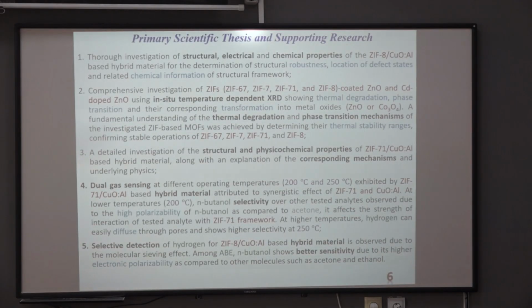The key primary scientific thesis involves the physico-chemical properties investigation of ZIF8 copper oxide based hybrids to get insights about their structural robustness, defect states, etc. And among all the different variety of hybrids used with zinc oxide, it gives insights about thermal degradation, phase transition and transformation in metal oxides, which provide information about how stable operations in a given temperature range can be performed for a variety of sensing applications.